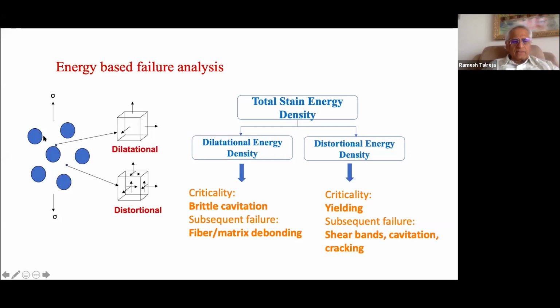So here's a non-uniform pattern. I'm applying remote stress sigma. If I go to a point like this, which is the polar point or close to the polar point, there's intersection of the axis of loading on the fiber, then typically I have dilatational or close to dilatational stress state. What that means is that all three principal stresses are tensile and equal or nearly equal. That is, you will have only volume expansion here.